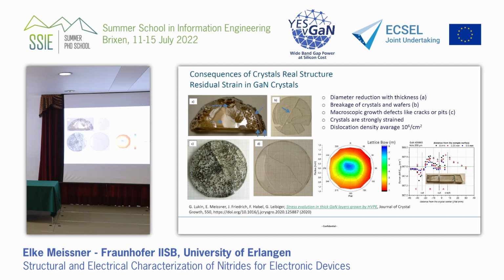Now you have something which is also important, which is residual strain. So fundamentally spoken, the crystal during the growth gets strained. If it gets strained, it may break on an atomic scale, which forms a dislocation, or not. So you have elastic or plastic deformation. A dislocation is nothing else than a plastic deformation to the crystal material, and as long as you have elastic deformation, you have no dislocation, but the crystal will be heavily strained. This is also something that you don't want, because in the next slide you will see what problem it causes, that the lattice may go. And this is also something you have to take into account.